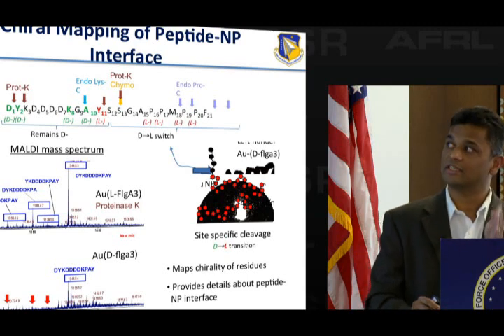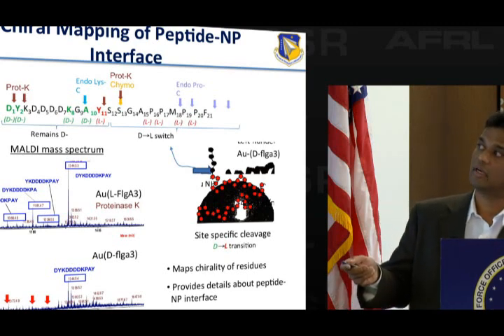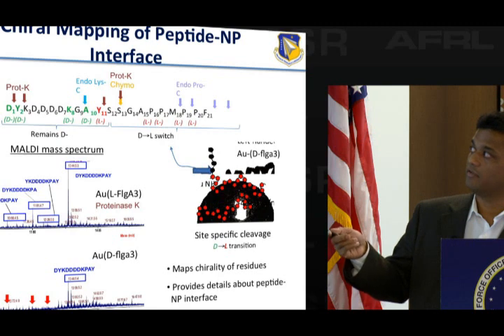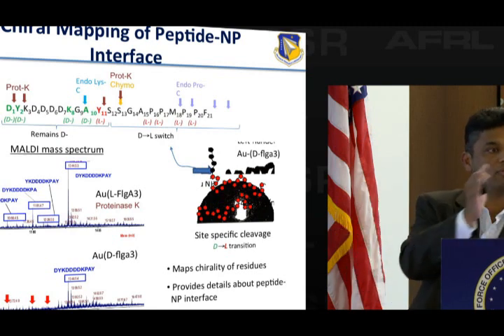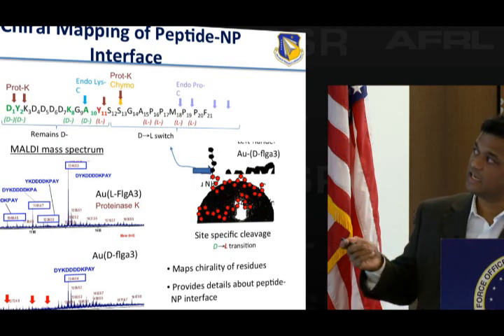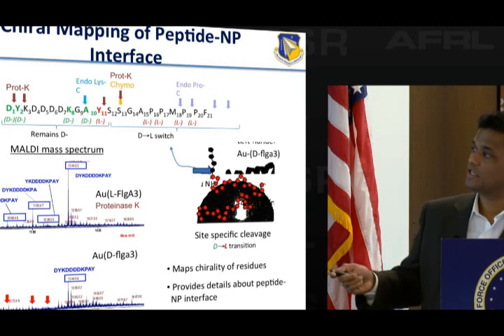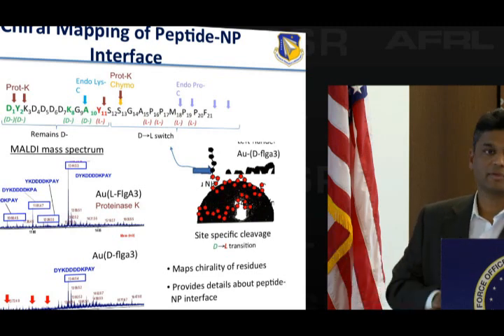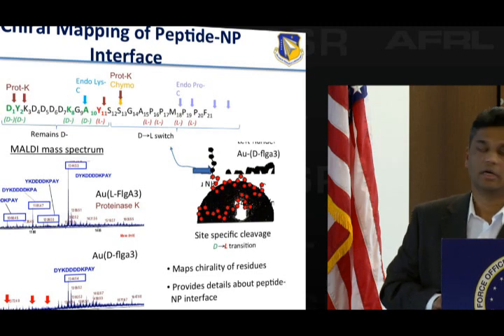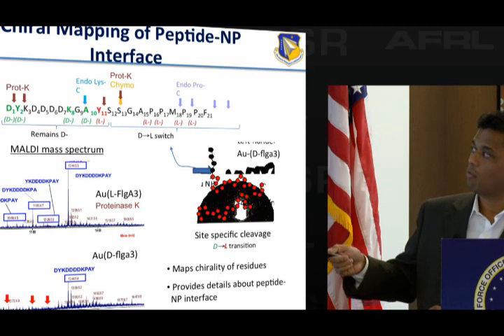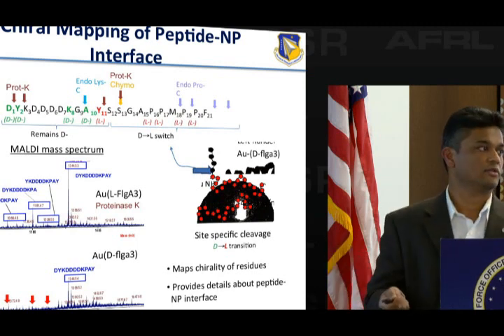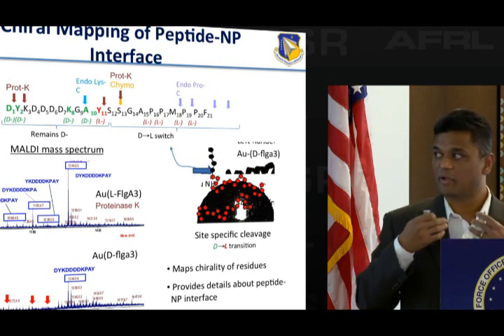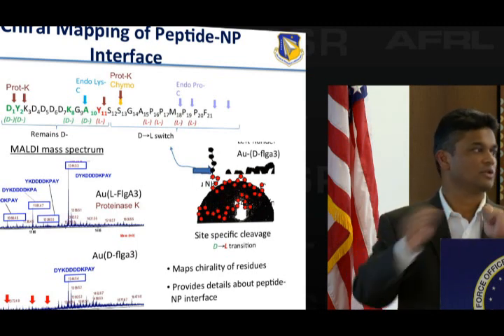We use proteins that can cleave at a variety of different sites. Proteinase K, for example, will cleave at a lysine and tyrosine. Endo Lys-C will cleave here. Chymotrypsin will cleave here. Endopro-C will cleave at the proline. So you can step through and map where the inversion takes place. And what we see is that the inversion takes place only in one half of the peptide, not the other half. The reason, from other studies through NMR and other things, is that this part of the peptide is away from the surface of the gold nanoparticle, so you don't get a transition from D to L. The part that's close to the surface of the gold nanoparticle, you actually get the transition. So you have to be in close contact, and there must be some kind of catalytic effect of the gold nanoparticle on the peptide that causes rearrangement of the bond.